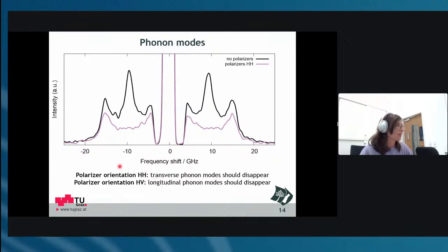So when I put in polarizers which are oriented the same way, so here horizontal, I should be able to just see longitudinal phonon modes, and my transverse phonon modes should disappear. That's the case here. You see the larger peak is still visible, but this one is nicely distinguished. You have some background, but that is because fibers are just a heterogeneous mess. So here you can easily determine, okay, this is my longitudinal phonon mode.